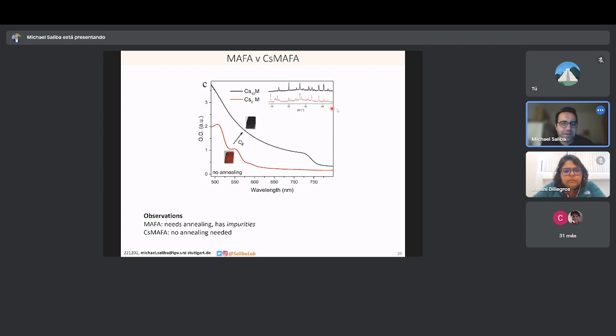So this kind of thing must turn into this one, and this introduces a lot of variability. I think that's the deeper reason, which I believe is now confirmed in literature as well, why these double cation perovskites are not very easy to reproduce for many groups. Whereas when small amounts of cesium are put in there, all of a sudden, all of this variability is bypassed. The material, because of seeded crystallization, starts from the correct perovskite phase from the get-go.